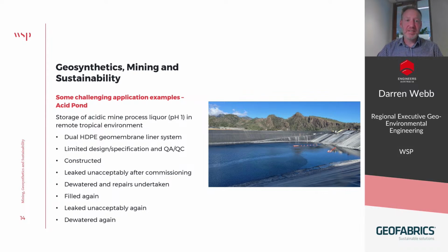It was constructed, it was filled, and after the first fill, it was assessed to be leaking unacceptably. So the owner then dewatered it and undertook a repair regime, filled it again. Very quickly, it was leaking unacceptably again, and then dewatered again. And this has all happened within 1 to 2 years of completion of construction. So you can imagine there was a rather frustrated owner.